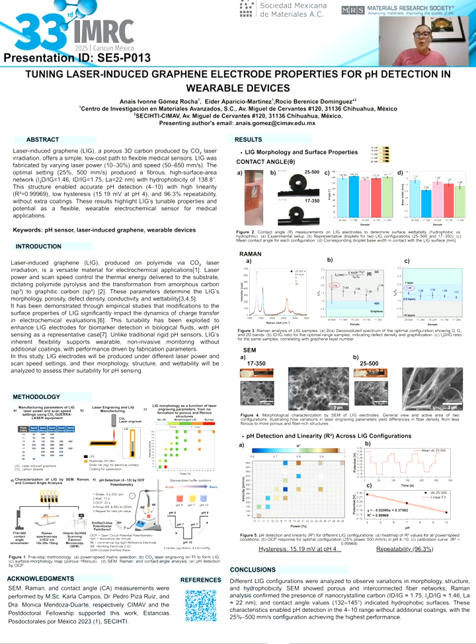Work conclusion. In this work, different LIG configurations were evaluated to establish the relationship between fabrication parameters and the material morphology, structure, and surface properties, aiming to optimize the performance for pH detection. SEM analysis revealed porous interconnected fiber networks, Raman spectroscopy confirmed the presence of nanocrystalline carbon, and contact angle measurements indicated hydrophobic surfaces. We were able to detect pH from 4 to 10 without any additional coatings.